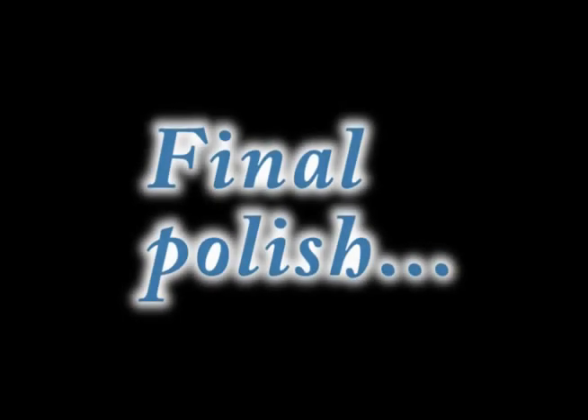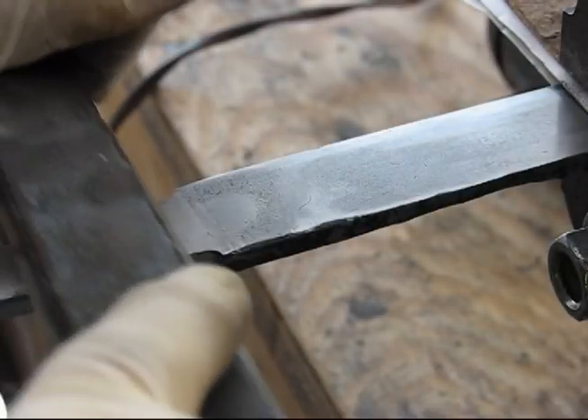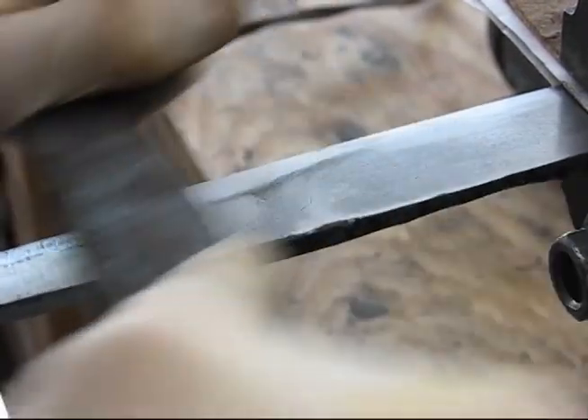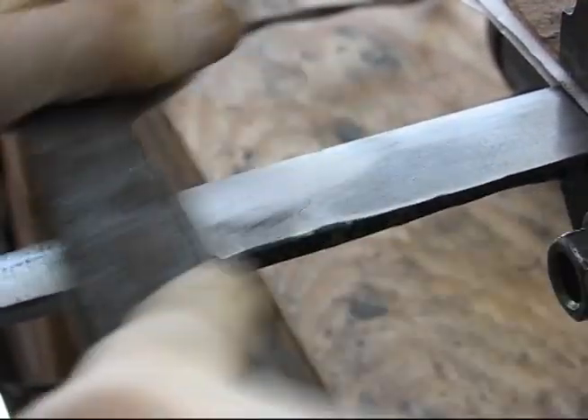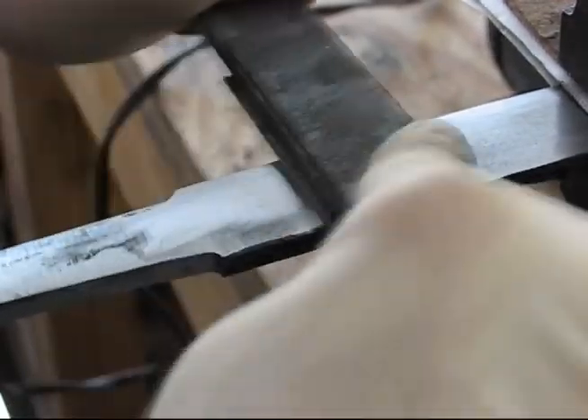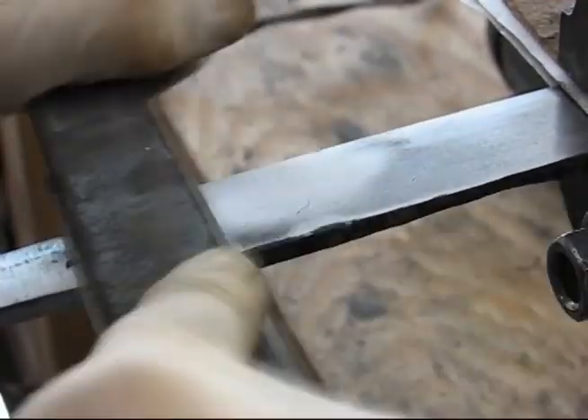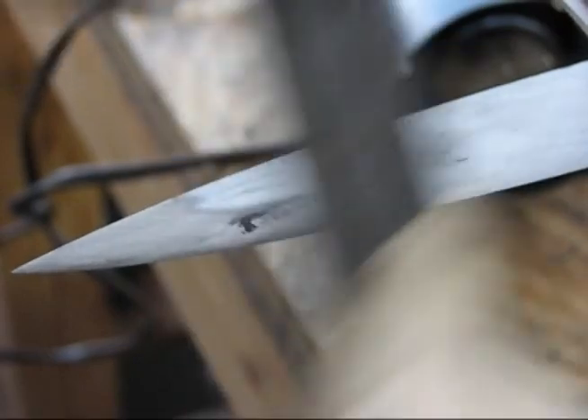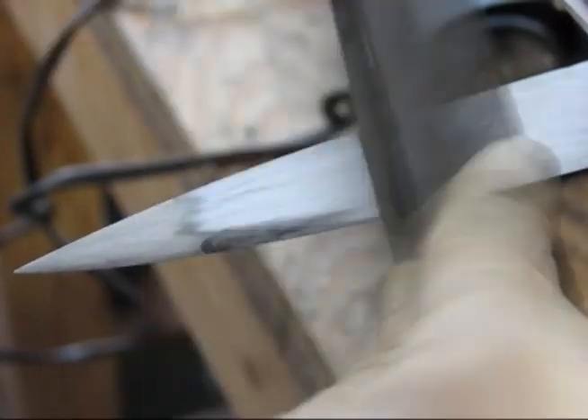The blade was at 220 grit polish, while we worked on all the furniture for it. It's time to move up the grit ladder and finish polishing the blade. Jesus will begin the polishing routine, starting at 320 grit sandpaper, backed with a hard metal bar that serves the purpose of being a two-handed grip sanding stick.